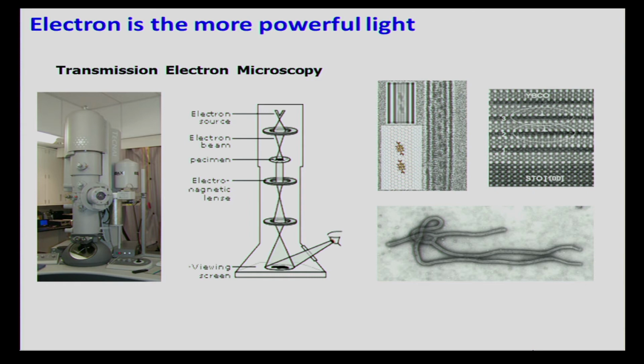This is one of our collaborators' work. This is basically a carbon nanotube. What you're seeing is the sidewall of the carbon nanotube. And what's amazing here is that you can actually see individual molecules of diamondoids that are inserted into them purposefully. Another example would be this high-temperature superconductor, the YBCO, sitting on a substrate. And what you're seeing here is each of these bright dots is a column of single atoms. And you can have atomic resolution to see the interface and the different layers in the substrate and in the YBCO.